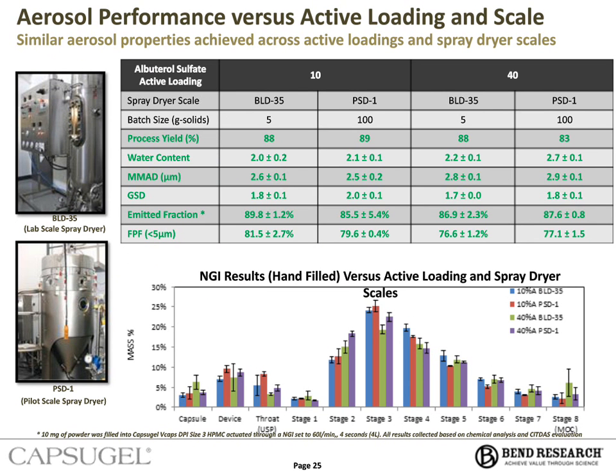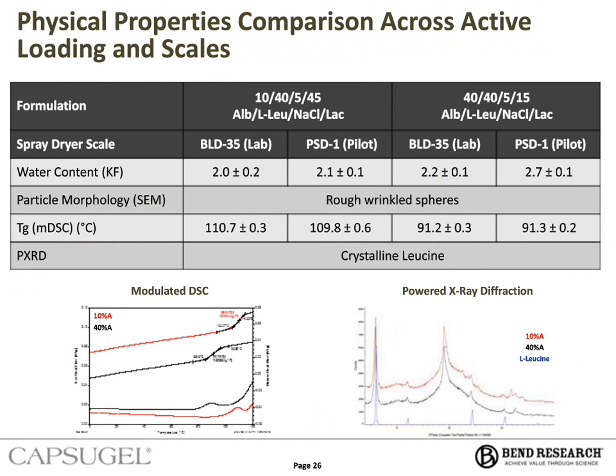And again, looking at some of the physical properties and other analytical tests that would be considered for these formulations that we discussed earlier. So the water content, which we've already shown, particle morphology, glass transition temperatures, and X-ray diffraction analysis. And so again, we see similar properties across scales with the 40% albuterol load, and albuterol being at slightly lower Tg. We see that decrease in Tg, but it's the same across the two different spray drying scales. And some example DSC and X-ray diffraction scans shown below.